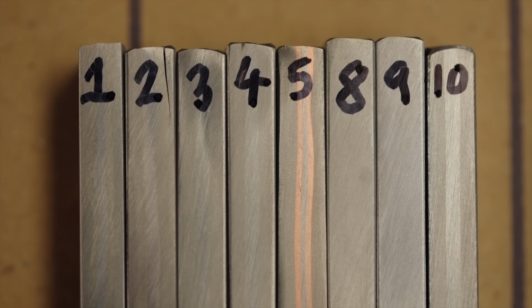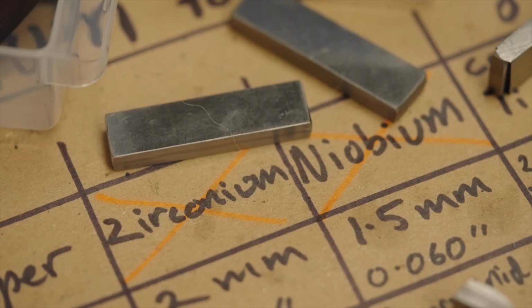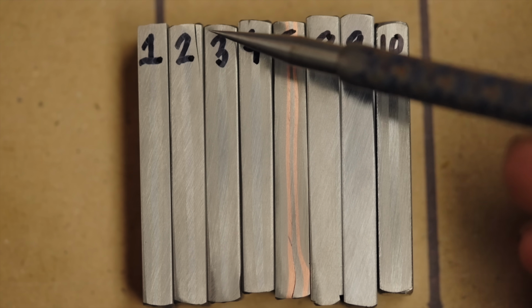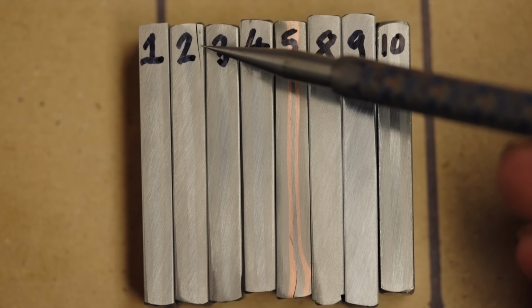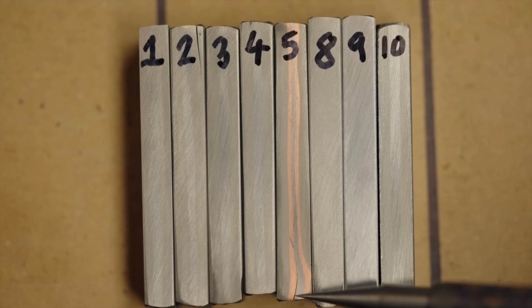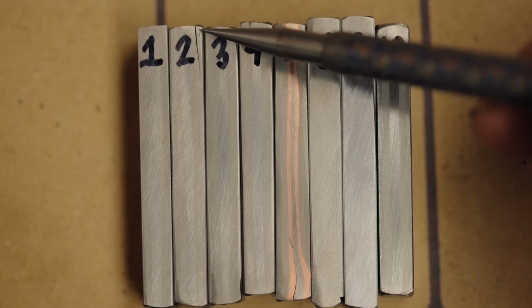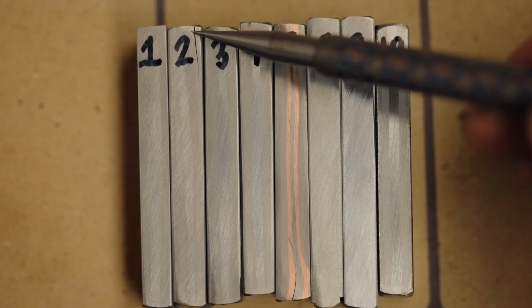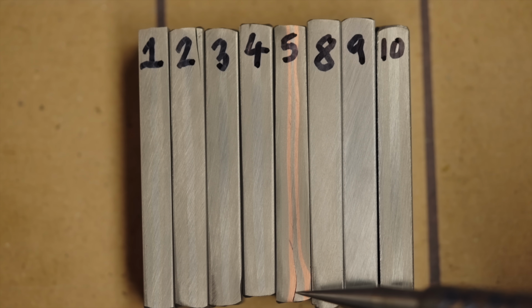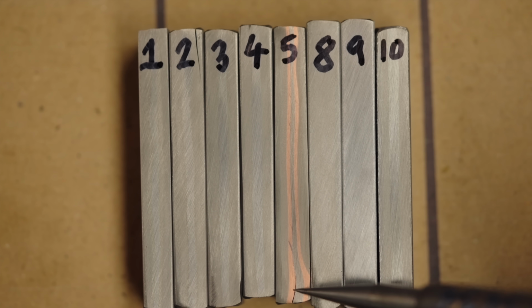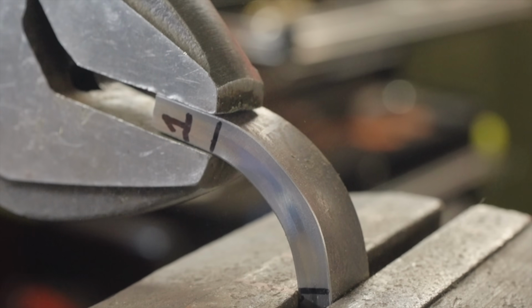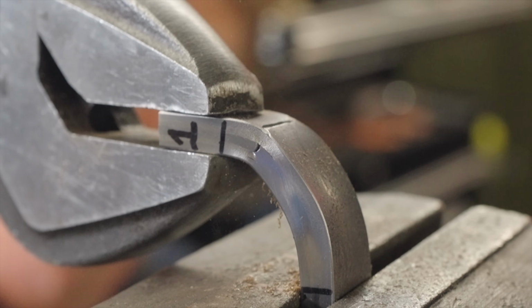And that is all of the heat-treated samples, minus those poor fellas. But it is worth noting we have a minor delamination at the top of 2, a minor delamination at the bottom of 5. The delamination on 2 is between the grade 5 and the grade 2 titanium, though. Delamination on 5 is between the steel and the copper. Let's get to testing. Oh my goodness, that was pretty good.